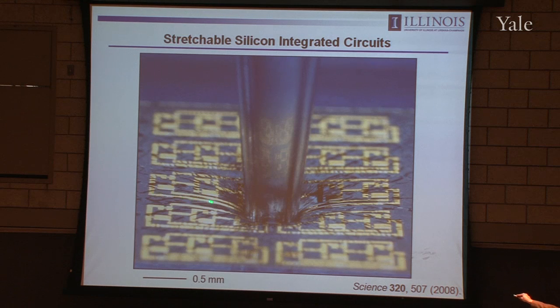And you can see this interconnect line, which was originally wavy and buckled in its shape like this one back here, has now been stretched out into a flat state to accommodate the tensile strains associated with that local force. So you can also imagine if you push this a little bit harder, that line would probably break, because it's been pulled flat. It can't accommodate much additional strain. So there's sort of a range of stretchability in these systems. It's about 15 to 20%. I'll come back to that in a second.